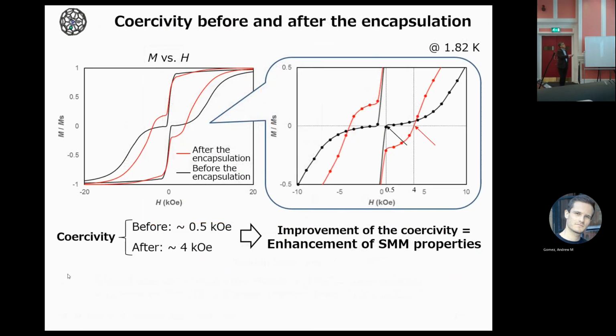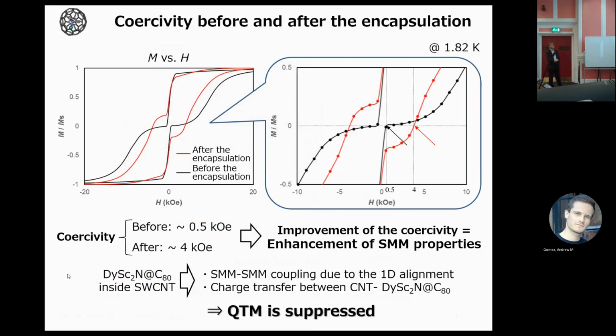And the interesting point is coercivity. Before encapsulation, coercivity is 0.5. After encapsulation, coercivity increases to 4 kilo. One order of magnitude increase. So this quantum tunneling is suppressed. So single molecule magnet behavior improves.